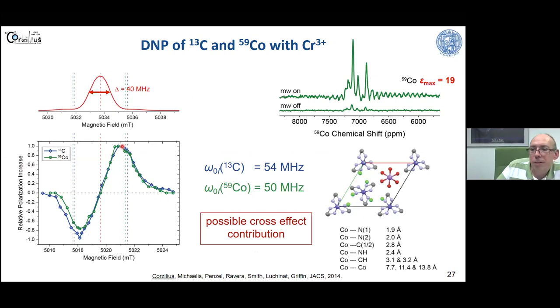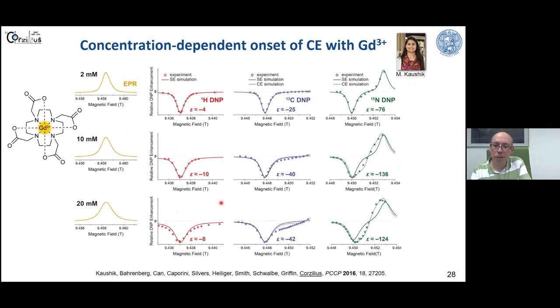Here we have already seen that there might also be a cross effect at work, not only the solid effect, which was unusual because we thought they are so far away that these chromiums don't see each other and cannot really talk to each other. And because they are sitting in a polycrystalline sample, the orientations of neighboring chromiums would usually be rather similar. But we could confirm this in another study looking at gadolinium in frozen solution, where we saw quite nicely for 15N that at higher concentration there was a clear deviation from solid effect and a significant contribution by cross effect. This is because in the frozen solution, the metal ions or the complexes can come closer together just by statistics at higher concentrations, of course.